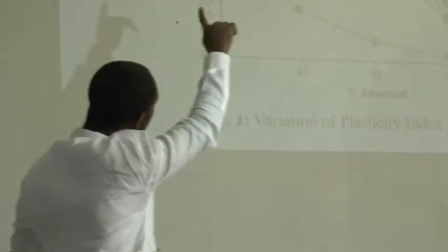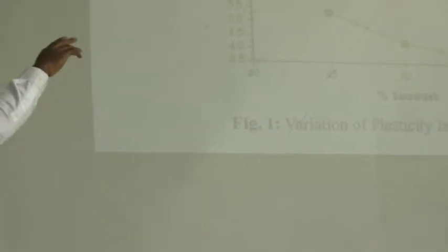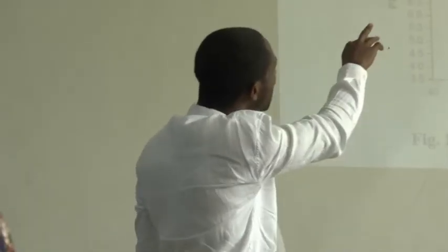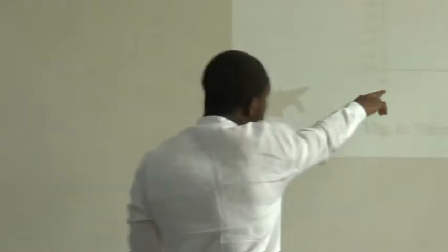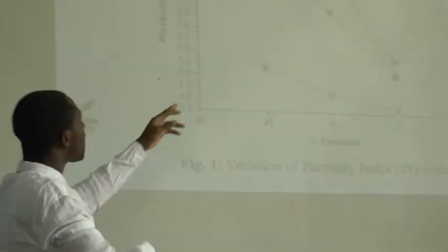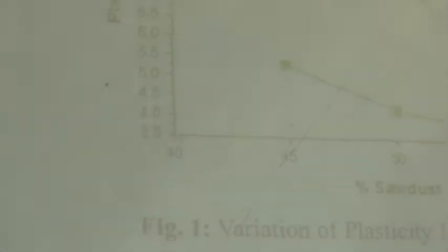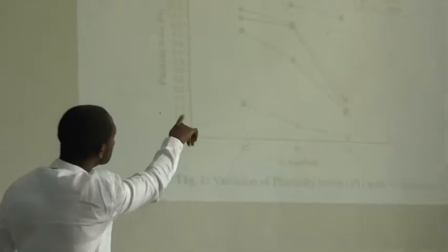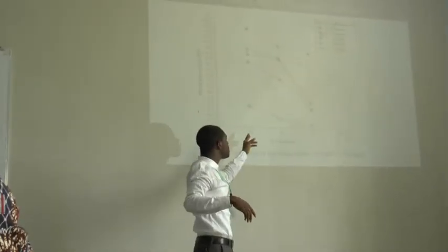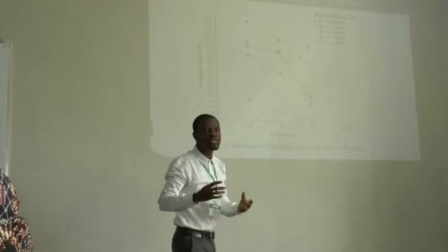In the samples, the purple, red, and the blue colors, there was a sharp decrease when the sawdust went from 50% to 55%. So the first 3 samples above were for the 1 to 0 blend of red clay and kaolin, and they have the highest plasticity. While the last one, the green color one, had a red clay to kaolin ratio of 0 to 1. That means the samples with only white kaolin clay and sawdust in the mixture have the least plasticity index.